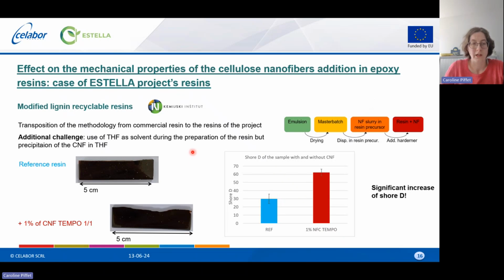Here we have an additional challenge, is that for those resin, we have to use THF as a solvent during the preparation of the resins, but the nanofibers precipitate in THF, so there is an additional incompatibility between the different components. So we have here the reference resin, how it looks like. And even with this additional challenge, we managed to add 1% of cellulose tempo nanofibers, so the very thin one. And you can see here, it's not very regular, but it's not very important. It was because of the mold. It's not on the quality of the samples.